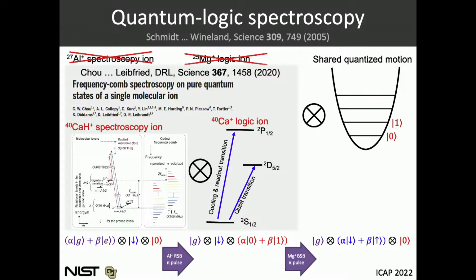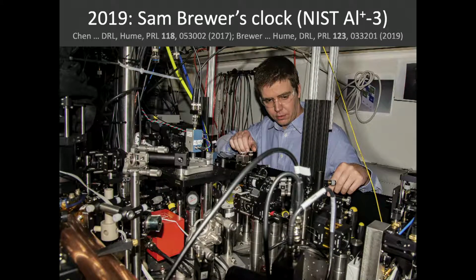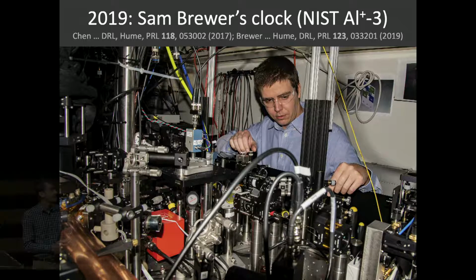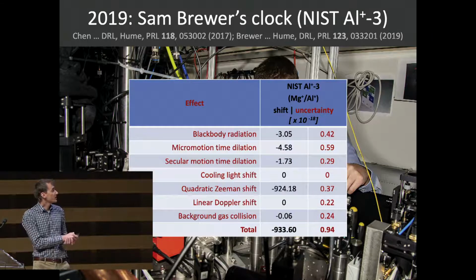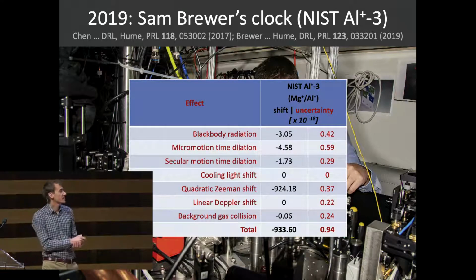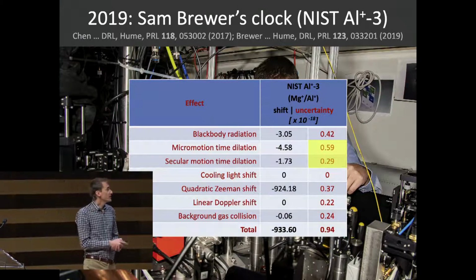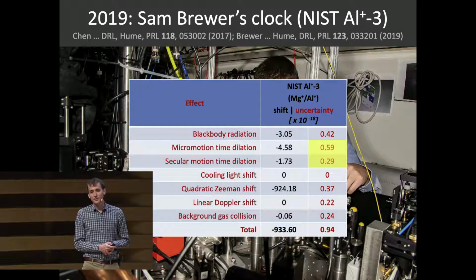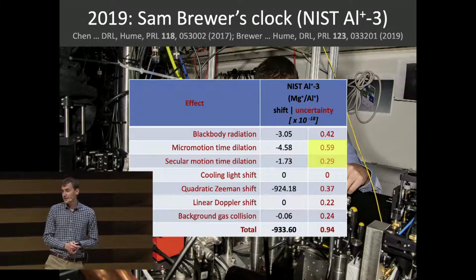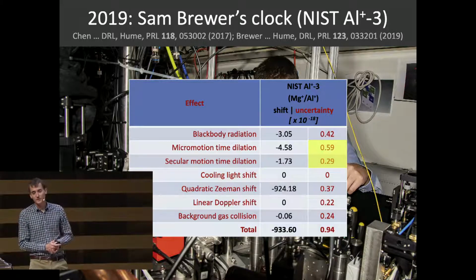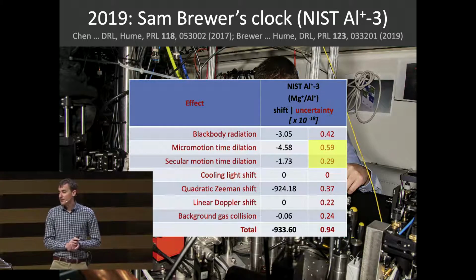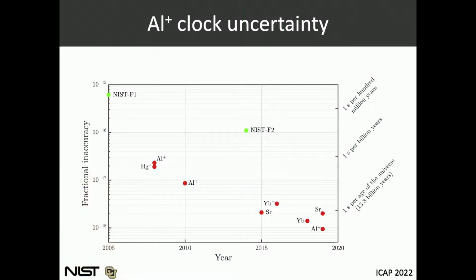Okay, but that's not really what I want to talk about. I want to talk about aluminum clocks, and in particular, I'll focus a little bit on this third generation aluminum clock we've had at NIST. And this was largely built up by a fantastic then postdoc Sam Brewer, who's now a professor at CSU. In this clock, we evaluated the systematic uncertainty, and I won't go through all of these in detail, but what I want to point out is that the total uncertainty here is slightly below 10 to the minus 18. It's limited by these two terms here, which are both second-order Doppler shifts. These are actually things that we've been working on improving already in our fourth generation clock.